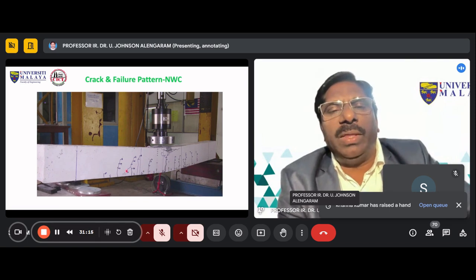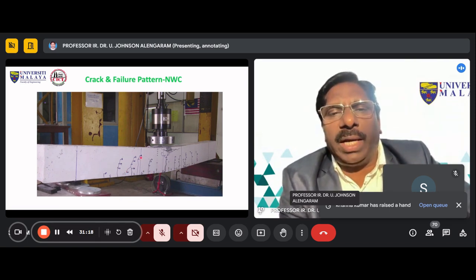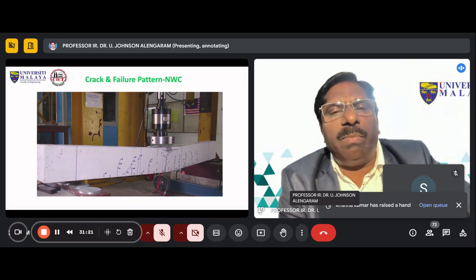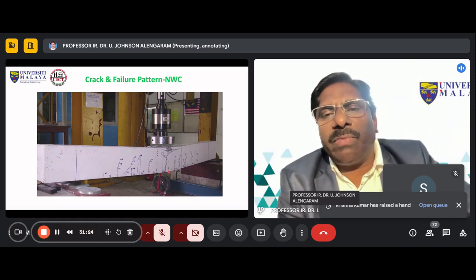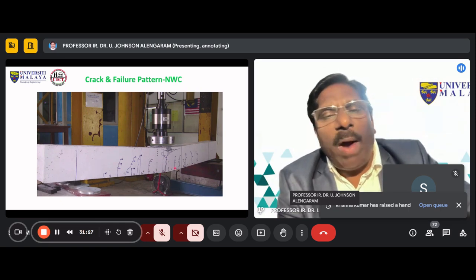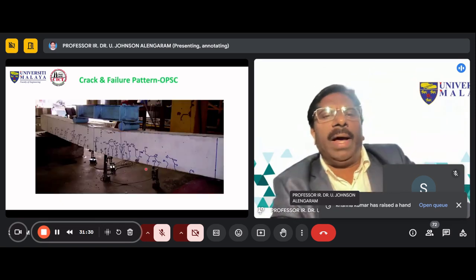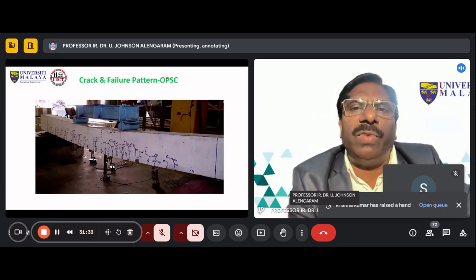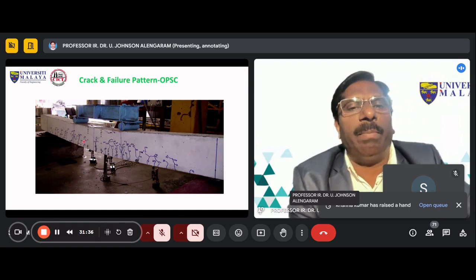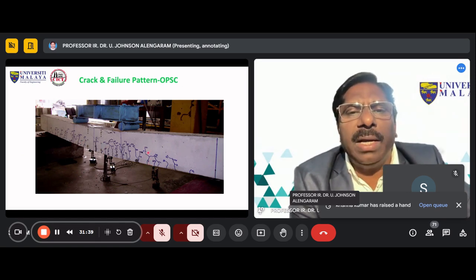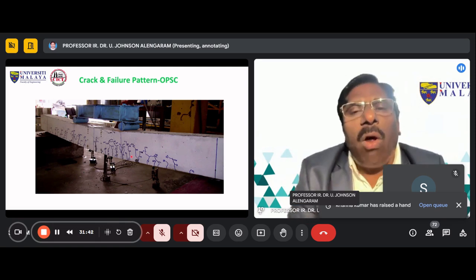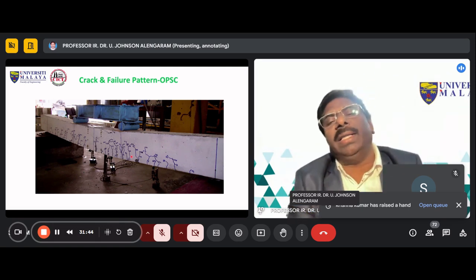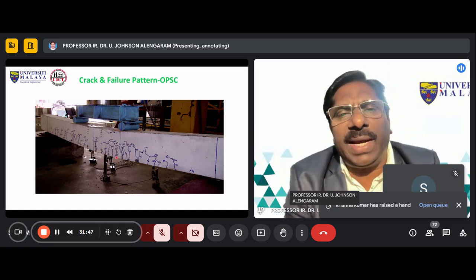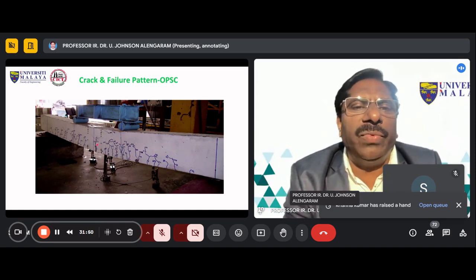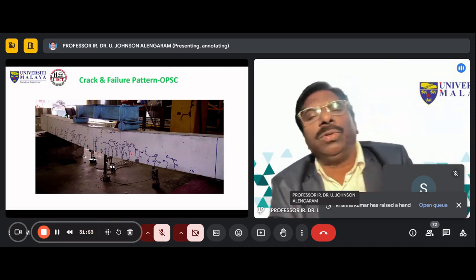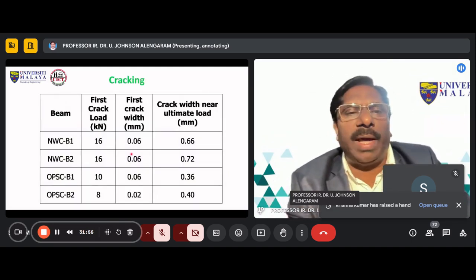This picture shows the normal weight concrete, where the cracking patterns are straight and there are a lower number of cracks. That means this crack will widen when we apply load, and the failure is brittle failure. Compare this with an oil palm shell lightweight concrete beam. See, the cracks are double compared to the other one and the cracks are zigzag. These zigzag patterns show aggregate interlock and also the bond between the aggregate and the matrix. Thereby, you see multiple secondary cracks, and also these cracks are not widened. Thereby, it shows the bond is quite good. So this one, no time to explain all.